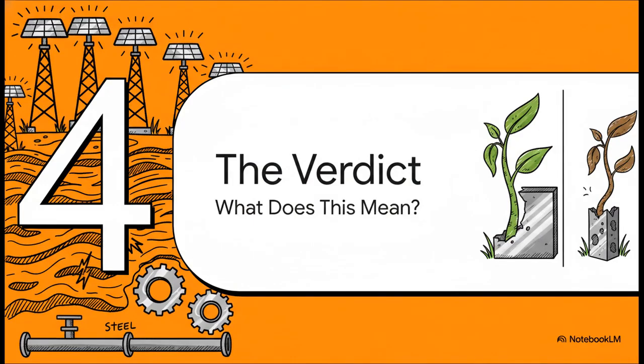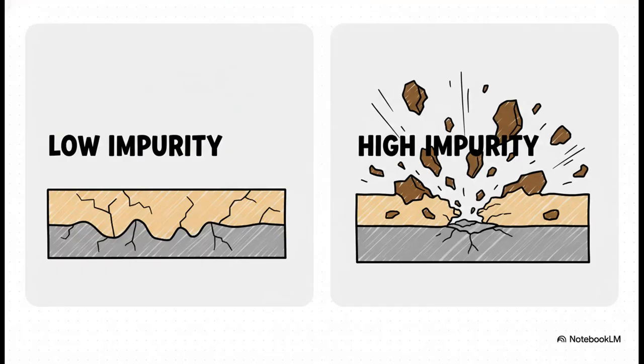So, after all that detective work, what's the verdict? What do these two very different results actually tell us about how to build better solar plants in the real world? Well, it really comes down to this clear difference. At super low impurity levels, you get non-uniform corrosion. The armor is there, but it's flawed, it's got weak spots. But once you cross a certain line at those higher impurity levels, the whole game changes. It becomes severe spallation, where the armor is just actively destroyed and flakes away, leading to really fast damage.